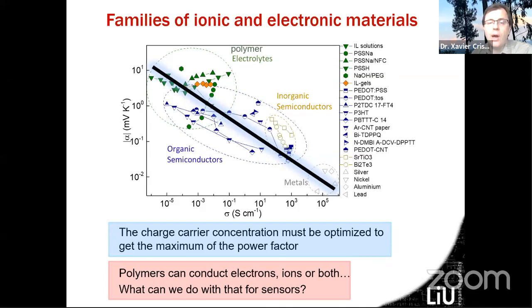On the contrary, if you have insulators with really little charge carriers, they typically have a large Seebeck coefficient, but they don't conduct anything, so it's not great. But looking at ions is also interesting, because these materials don't conduct electrons, but they conduct ions, and that leads them to have a Seebeck coefficient which is actually quite high. We reach nowadays in polymer electrolytes something like 20 millivolts per Kelvin, while metals have microvolts per Kelvin - so a much larger number.